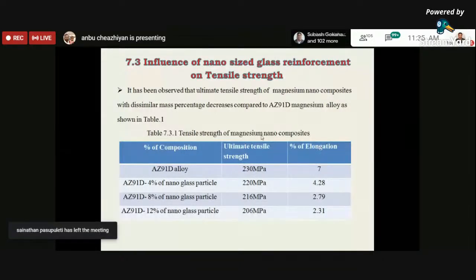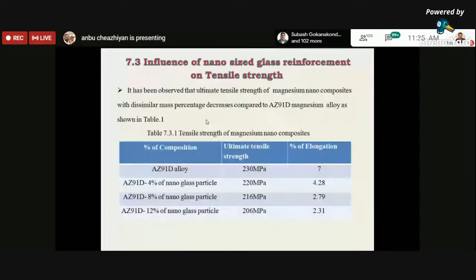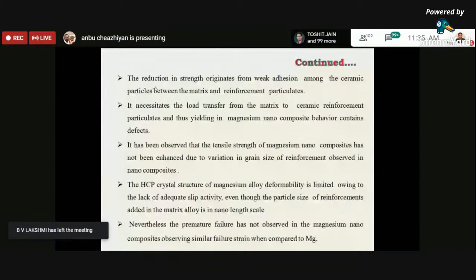So it has been observed that the ultimate tensile strength of magnesium nanocomposite with the dissimilar mass percentage decreased compared with the AZ91D magnesium alloy. So it's not increased; it has been decreased. Here, the reduction in strength originates from weak adhesion between the ceramic particles, the matrix and the reinforcement particles. Hence it necessitates the load transfer from matrix to reinforcement particulates, and hence the yielding behavior of magnesium nanocomposites contains defects.